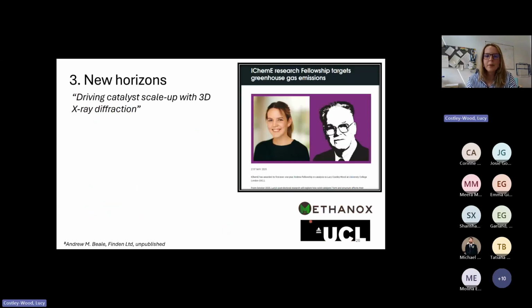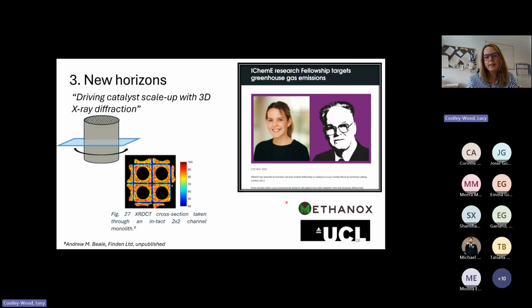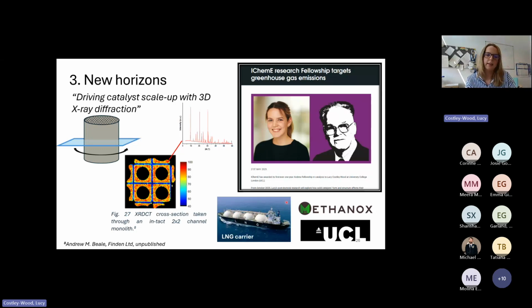Just to finish off, I have been awarded an IChemE research fellowship entitled Driving Catalyst Scale-Up with 3D Diffraction. The aim is to be able to do XRD CT, so three-dimensional XRD, on an intact monolith during operation. From this, build up a picture of what the catalyst looks like during operation for something even 10 centimeters big. And then from each pixel of this CT-like image, we'll be able to pull out a diffraction pattern. And this will really help with the scale up to understand what's happening inside the monolith, at what point in the channels, at what point in height. And the application of these catalysts is for LNG carriers, so in the maritime industry.